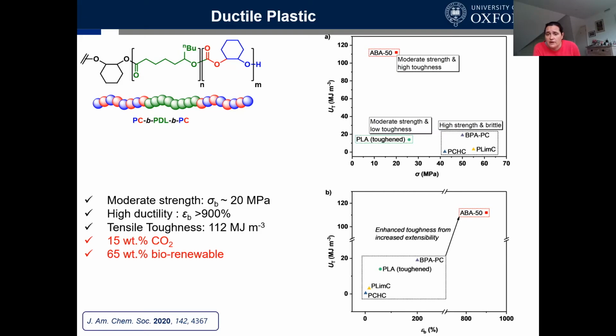And you can see that we've really hit a nice regime for our new 50-50 composition polymer. It's much tougher than PLA, which has already been toughened, or than bisphenol A polycarbonate or various other polycarbonates, much tougher than the polycarbonate on its own without the green block, so showing you the benefit of having that present. And again, plotting toughness against stress at break, we can see that it's got a moderate strength, certainly within the range of usable materials, but a really high toughness.